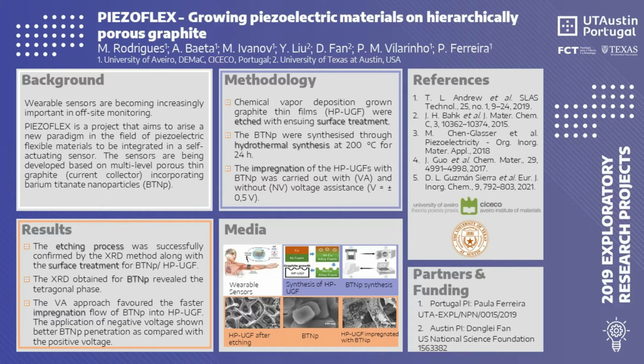The synthesis of barium titanate nanoparticles was achieved through a bottom-up method called hydrothermal synthesis, and the one implemented here is a modification of the procedure used within the Portuguese group, where the two barium titanate precursors were added to sodium hydroxide in an autoclave for 24 hours at 200 degrees Celsius. The particles were dispersed in water and tested for the ideal pH to achieve a good stability.